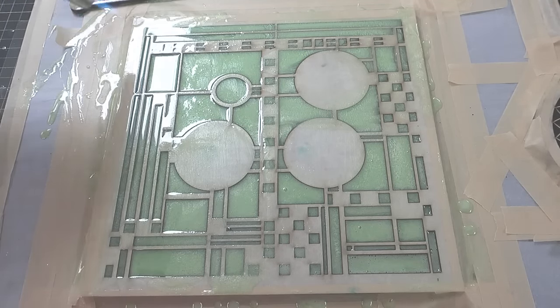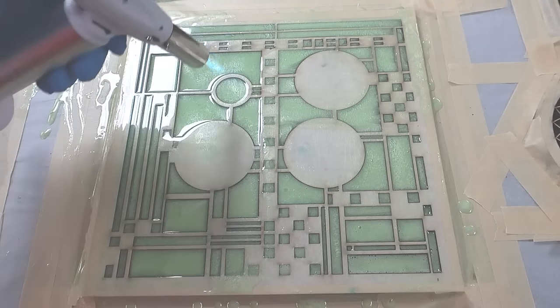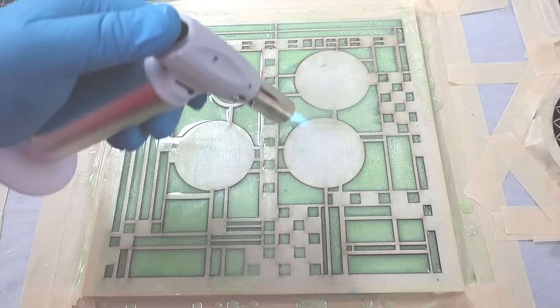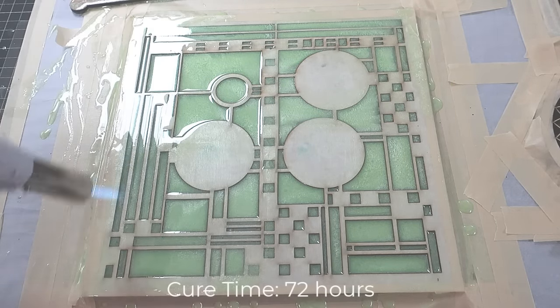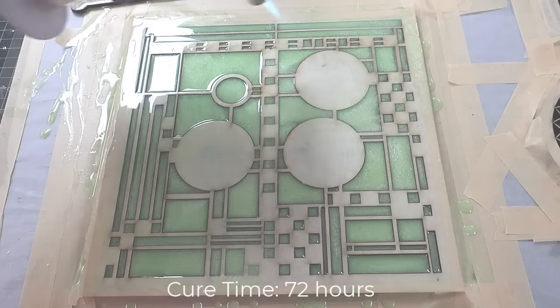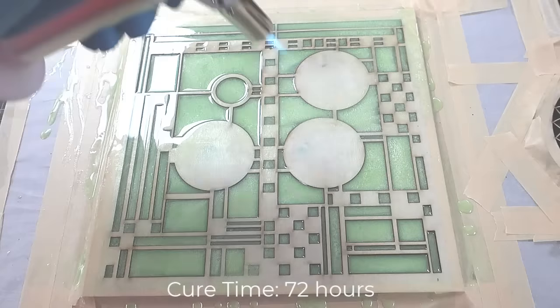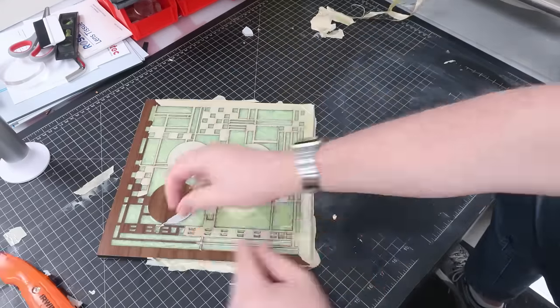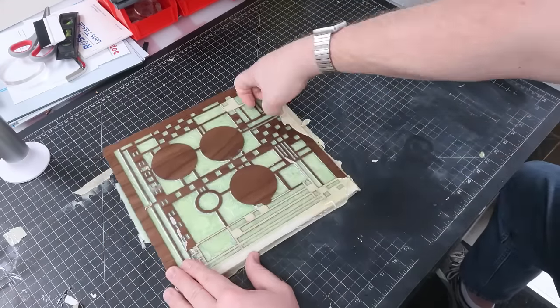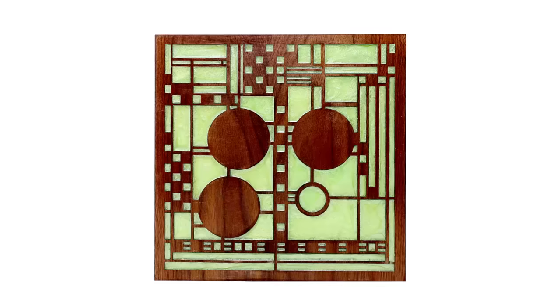flame the surface. Unlike the UV epoxy, you must flame the bubbles away every 5 to 10 minutes for the first hour or so as it starts to set up. Then, let it cure for 72 hours or 3 full days. Once cured, remove the mask for a finished stained glass looking effect that can be backlighted.